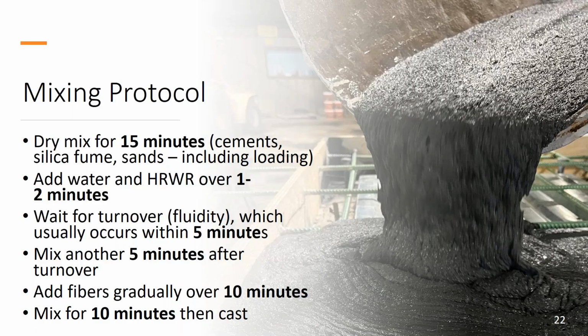It says here 10 minutes, but that's really a practical limitation of adding the fibers because they come in bags. And so you kind of dump them in one after the other. It takes a while to do so. And then you mix for another 10 minutes and then you cast.